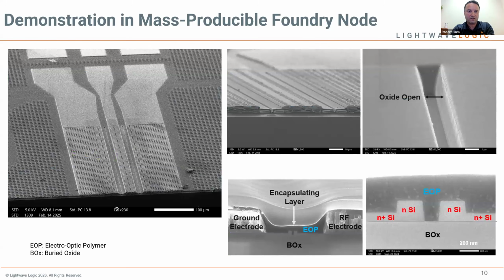And so if you look at some of the structures that we have produced in the past, again, this is just to show you what it looks like in principle, but you can see, if you look on the bottom right, you basically see the electro-optic polymers filled into the slot. And what is interesting here is basically we don't have a PN junction. It's just N-doped silicon on both sides. And you basically have that to be able to get the electrical field to the slot. But then the mode is really in the silicon and in the EO polymer that is in that slot.